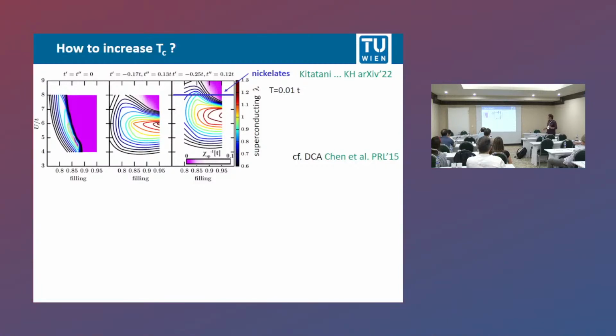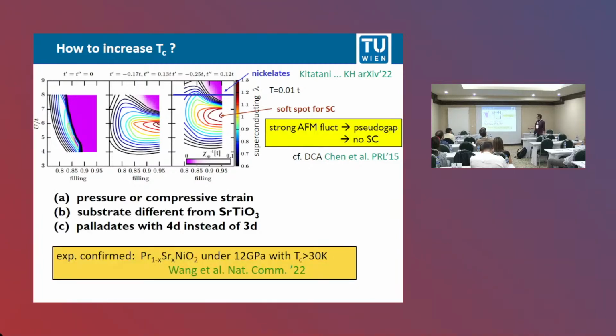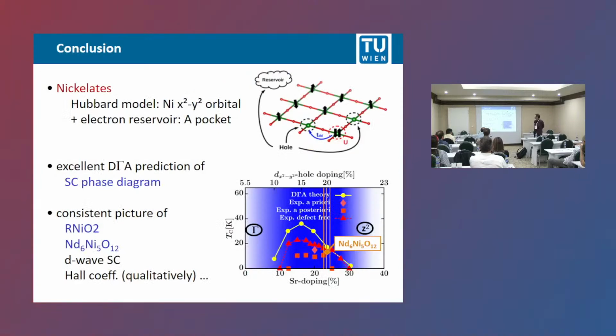Let me just briefly say how to increase TC. We see that one should have a lower Coulomb interaction to hopping ratio. That is possible by using, for example, pressure, and that has been spectacularly confirmed experimentally: at 12 gigapascal you have the nickelate superconductors with the largest TC of 30 Kelvin nowadays. So that matches, and with this I come to my conclusion.